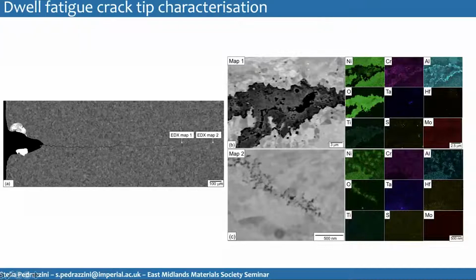But looking at an interrupted test, this all made a lot of sense, because we're observing the exact same thing that we observed in the secondary cracks. So there is some chromia and some nickel oxide, a whole variety of different oxides, some titanium oxide in the crack, and some alumina all around. And then sulfur and molybdenum form all these dark particles that look exactly like the ones around the secondary crack at the grain boundaries around the primary crack. So this was from the middle of the primary crack.